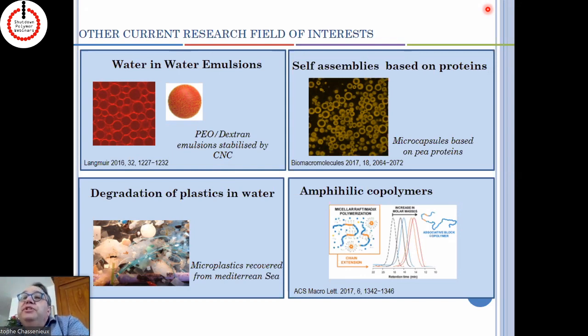The only way to achieve this is at one stage, which is exactly what people do when they do a nanoprecipitation, to have a state during the processing and during the dispersion of your polymer where the system is at thermodynamic equilibrium. So the only way to achieve this in our case was to process the polymer at very, very high temperature in order to decrease to a large extent the surface tension of the hydrophobic block. So there are some conditions.